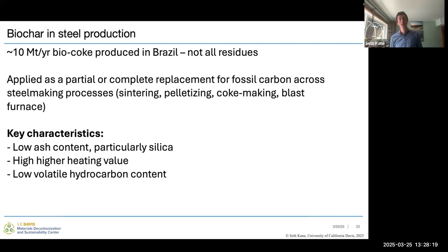Higher heating value is going to be more beneficial. All of these are going to be a little bit lower than fossil-based coke for their higher heating value, but the closer we can get, the better. And then you want to have very low decomposition at low temperatures, so you can really allow that process to get up to the high temperatures that we need for steel making without having any degradation.